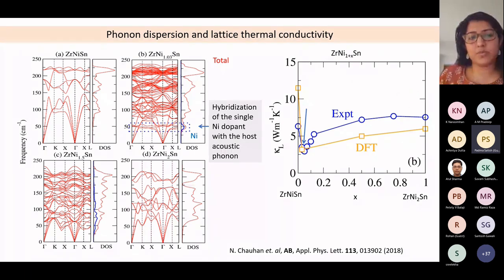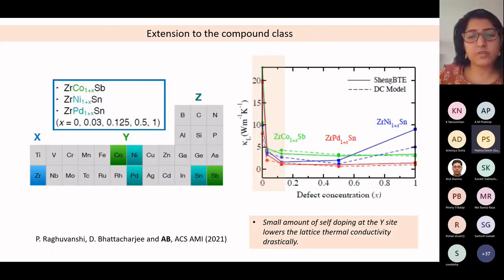When we did it for the first time, we did it with one particular compound, which was zirconium nickel tin with a little bit of Y site substitution. And we found there are some rattling modes of nickel at very small doping concentration, which do not appear as soon as the amount of nickel concentration in the system is more. So therefore, what we did is we tried to see whether this is a phenomenon across all the half Heuslers or not.